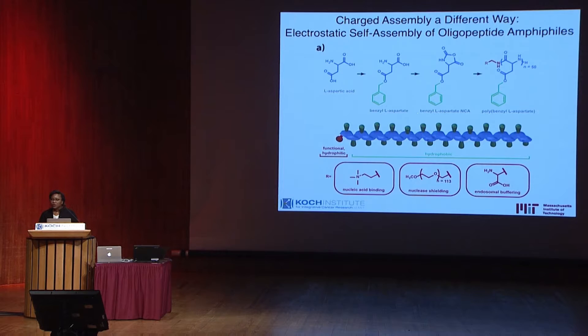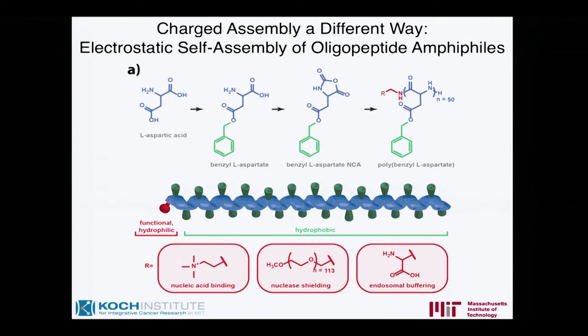My last story is another collaboration. I'm going to talk about a different way we can assemble using electrostatics. We've developed a range of oligopeptide amphiphiles which assemble based on charge in the presence of nucleic acids—based on poly-L-aspartic acid, forming a very hydrophobic alpha helix. What we initiate this system with gives us a hydrophilic head group: nucleic acid binding, nuclease shielding via a short PEG chain, and an endosomal buffering group—a zwitterion—which allows us to exit the endosome, critical for siRNA delivery.